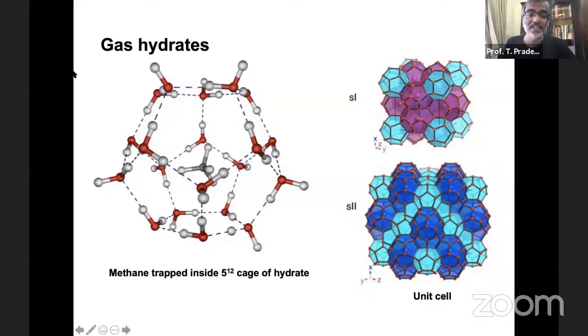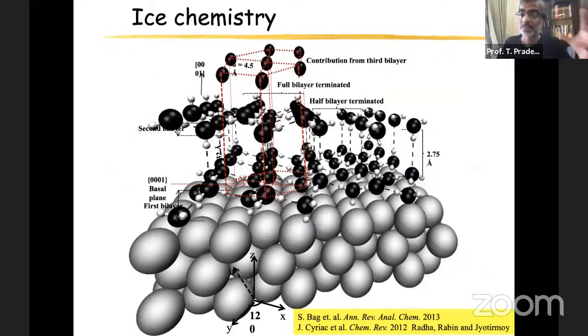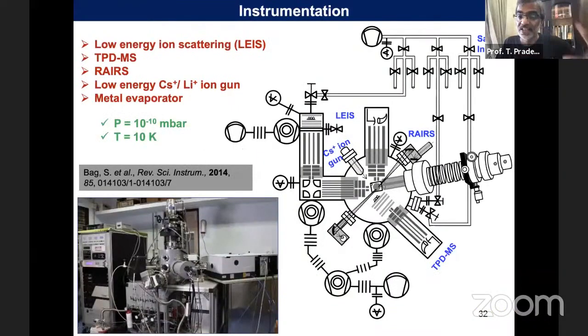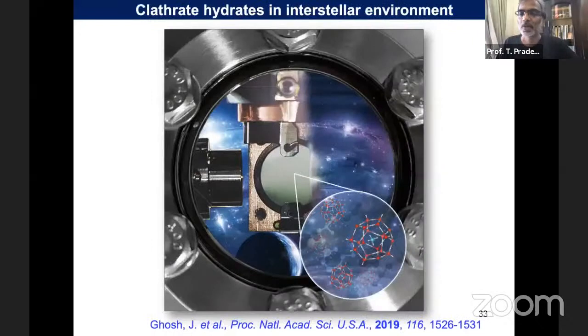Gas hydrates are cages like these wherein molecules are trapped, and you can create interesting structures. They form at generally high pressures, but you can also create them in a laboratory atmosphere, as in ultra-high vacuum. So we have built an ultra-high vacuum instrument wherein you can deposit molecules of water layer by layer on a single crystal. And this is an instrument that we have built, which can be used to probe such materials using several tools, including infrared spectroscopy and mass spectrometry, secondary ion mass spectrometry, and temperature programmed desorption and things like that.